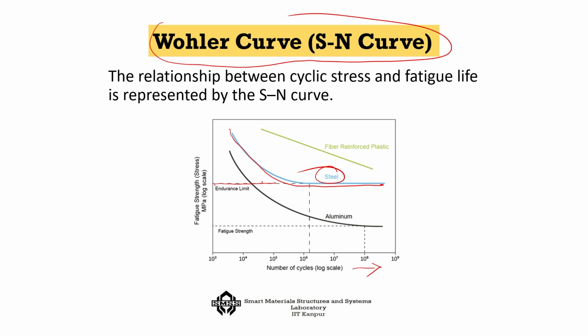But say, for example, fiber reinforced plastic, you will never see this happening; it is continuously coming down. Even for aluminum, it does not exactly saturate, it continuously comes down. That is why the endurance limit is not very clear for them, but for steel you get a distinct endurance limit. And this limit is, as I told you, maximum up to 0.6 of sigma_u. Okay? So, that is how, whenever we get a sample that you need to test for fatigue, we actually obtain the S-N curve, the total number of cycles that we can withstand, and from that we try to get the endurance limit, etc.